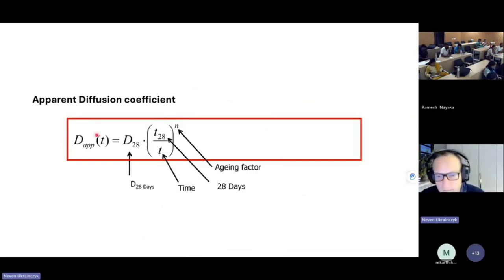So the time-dependent diffusion coefficient in the Eurocode or the fib Model Code 2020 is modeled using the migration coefficient from the RCM, the rapid chloride migration test. This is not really the real diffusion coefficient. It correlates, but it's not the real diffusion coefficient. But this is the approach, because you need rapid measurements and also rapid predictions. We cannot wait.